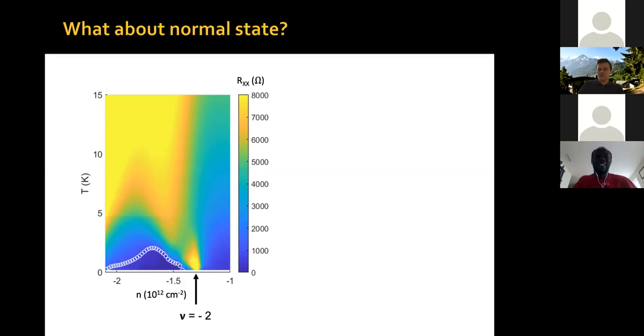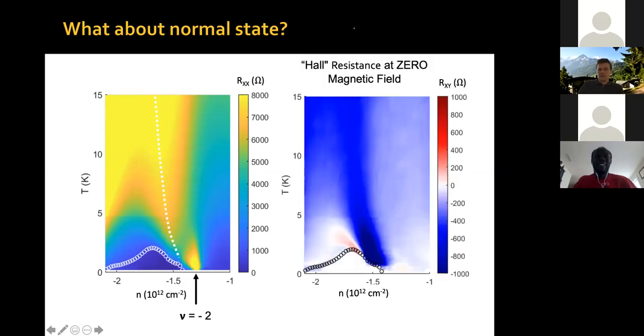In principle, because I'm at zero magnetic field, if the system is isotropic, I should measure zero transverse resistivity. But look at, oh, sorry, and by the way, just to remind you, this is this banana feature, this depletion in TC, this is the correlated insulator state for holes. I'm just placing now this white line without any adjustments on top of this diagram. You can see that in the region where we have this resistance maximum here, which leads to the competition with the superconducting state near zero temperature,